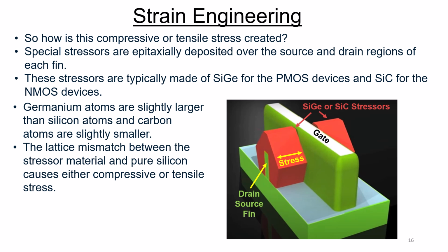Now, how is this done? To show how this compressive or tensile stress is created, special stressors are epitaxially deposited over the source and drain regions of each fin. And that's what these red areas are in this drawing below here. Now these stressors are typically made out of either silicon germanium for the PMOS device or silicon carbide for the NMOS device. Now germanium atoms are slightly larger than silicon atoms, and carbon atoms are slightly smaller.